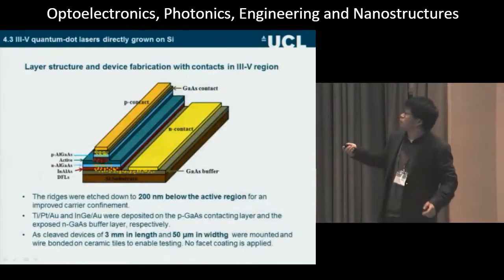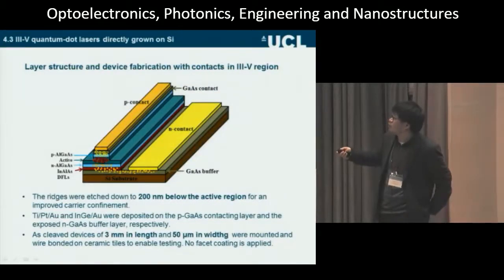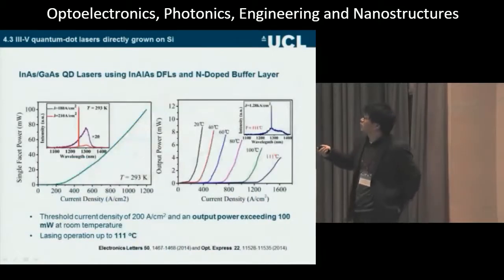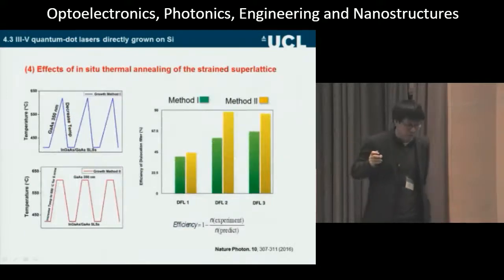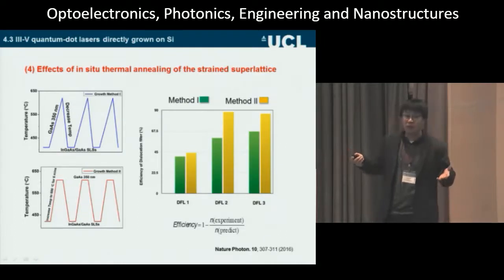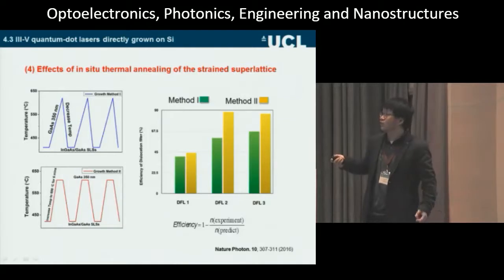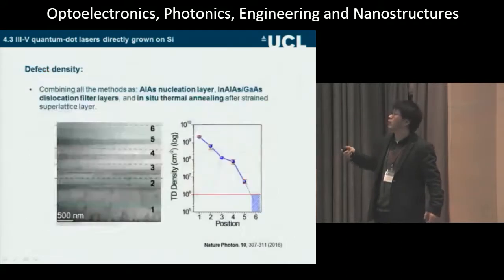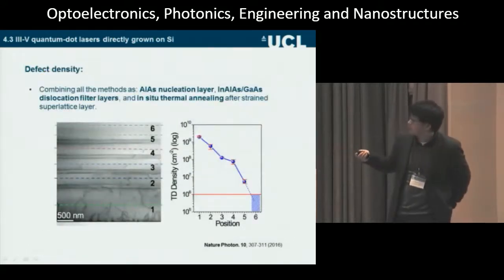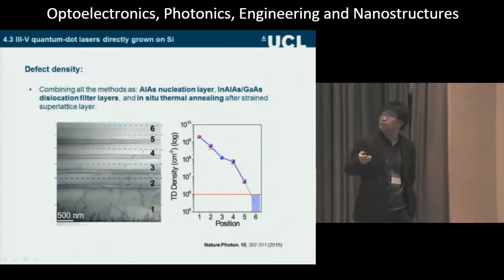Also, this time we do proper P contact and N contact, and also top-top contact. So that's the first result we got at room temperature, with 100 milliwatt power and laser operation over 100 degrees. The most important thing, I believe, that we did is another growth technique, so-called in situ annealing. When you grow dislocation filter layers, normally after them we grow gallium arsenide. For this one, we just give a few more minutes to anneal at a higher temperature. You can see the dislocation annihilation rate is much higher. That's the TEM picture with the annealing. After 4 repeated dislocation filter layers, in the cross-section TEM we can't see any defects. It's in the 10^5 range.